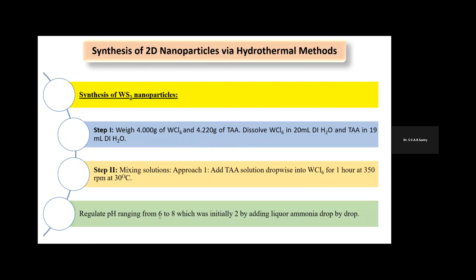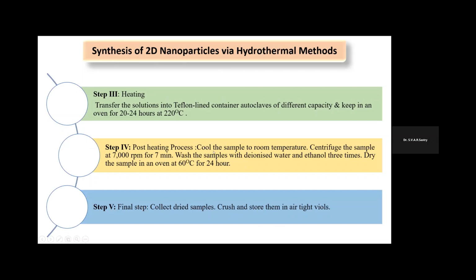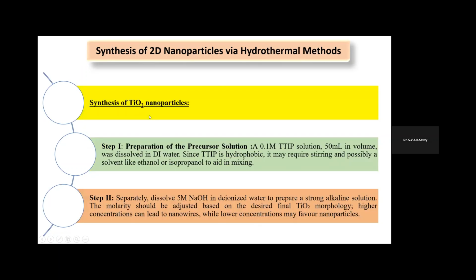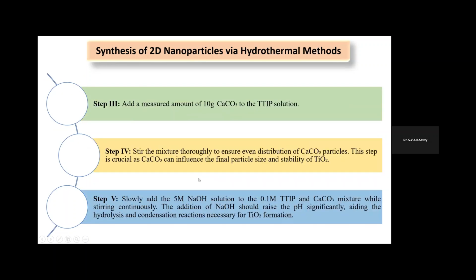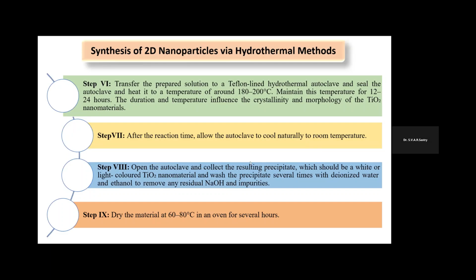Then tungsten disulfide nanoparticles: here the precursors used were WCl6 and TAA, and then it was kept in the autoclave. The temperature was 220 degrees Celsius, and the time was around 20 to 24 hours. Then coming to TiO2 nanoparticles, here TTIP solution was the precursor, and the temperature in the autoclave was kept at around 180 to 200 degrees Celsius, and the time was around 12 to 24 hours.